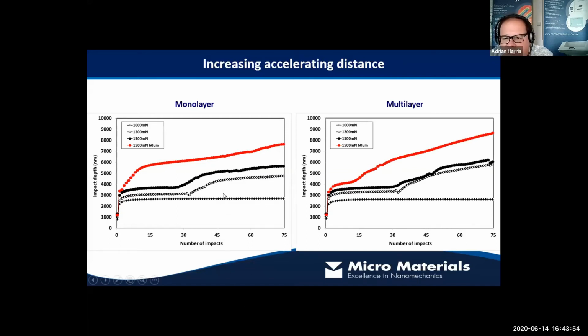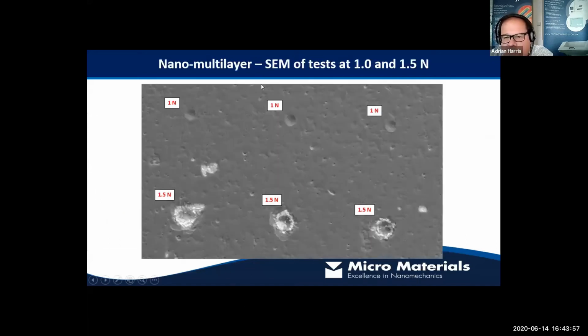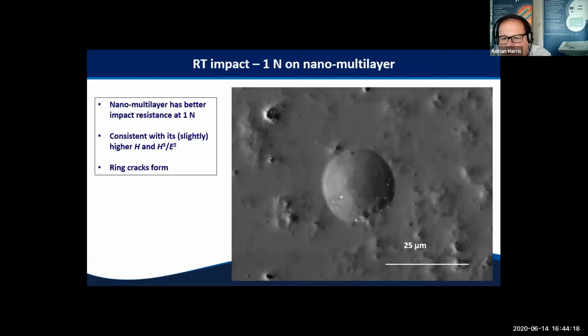Here are some SEM images of our impact sites on the multi-layer sample at 1 and 1.5 newtons. So 1 here, 1.5. The 1.2 newton tests were done afterwards because clearly the transition in behavior is somewhere between 1 and 1.5 newtons. So let's look at these in a bit more detail. Here's the 1 newton impact site on the multi-layer coating.